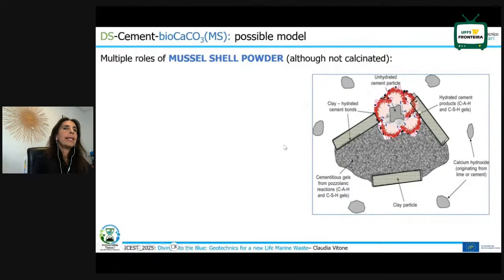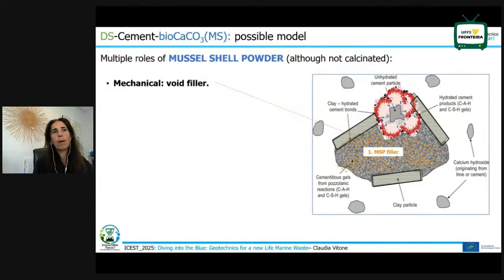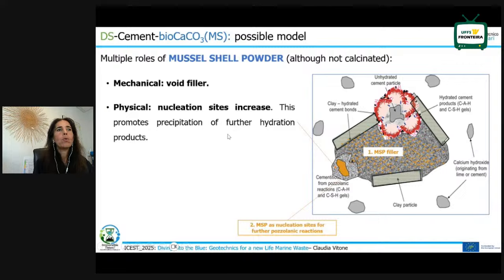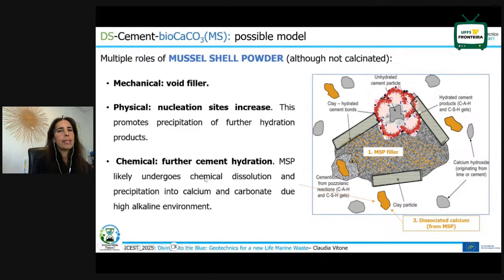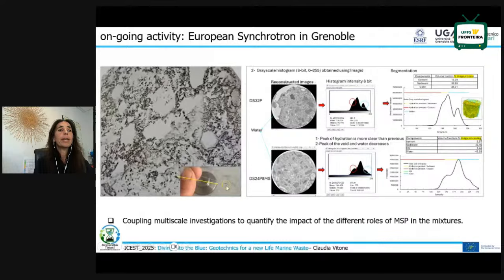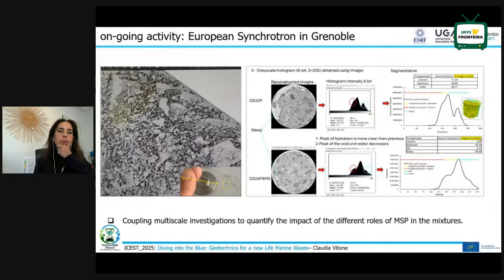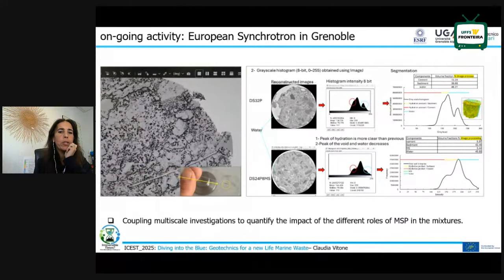So to sum up, the possible model that is explaining why this biogenic calcium carbonate is so effective is made up of three main roles, essentially. The first one is filler, because this powder is very fine, so essentially it is filling. But not only, because there is also a physical role as an increase of nucleation sites, and also a chemical one, because as I already explained, due to the alkaline environment induced by the presence of cement, there is a dissociation between calcium and carbonate, and so this promotes further pozzolanic reactions. We are now working with other PhD students trying to explain and quantify the relevance of each of these roles in these mixtures.